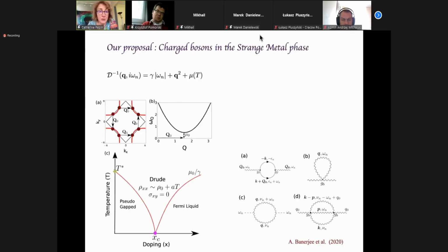So we decided to do a transport calculation with Kubo formalism with charge 2 bosons. To our dismay and surprise, it's never been done before, which is also typical of cuprates. You go to one line of thought and you develop theories, but then we changed the line of thought by putting bosons everywhere, and especially charge 2 bosons, and it's never been looked at. For example, nobody has looked whether they could form at high energy, very close to 1 eV, so the energy of the Hubbard model or 3-band Hubbard model, whether bosons could be formed there. Nobody has looked at it, and this is some answer that we can get theoretically, probably.